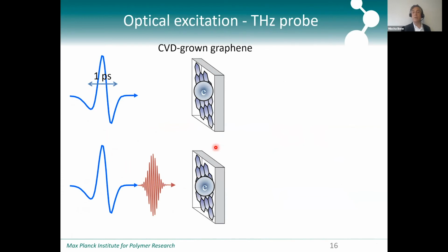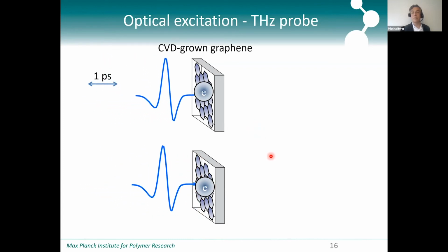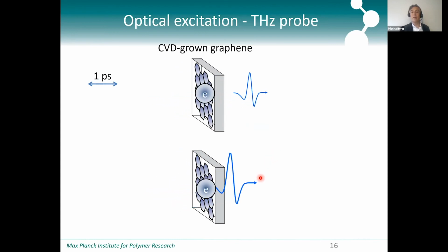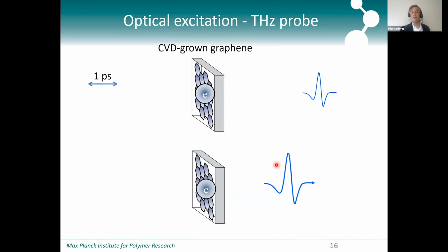And so we now do a different kind of experiment. So we photo-excite the graphene here, we photo-excite the carriers, and the reference measurement is now the transmission of the terahertz through the unexcited graphene. And again, here are my not so great skills of animation in PowerPoint. You will see that there is a difference, or we find that there's a difference in the transmission. So we see that we have more transmission through the optically excited graphene.